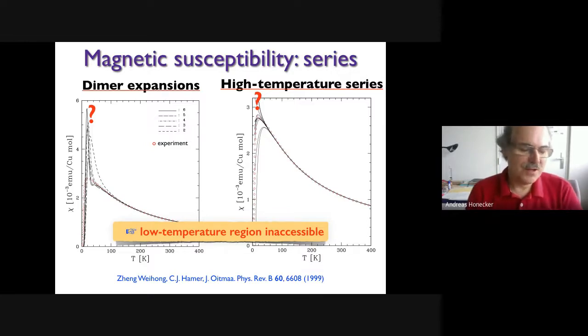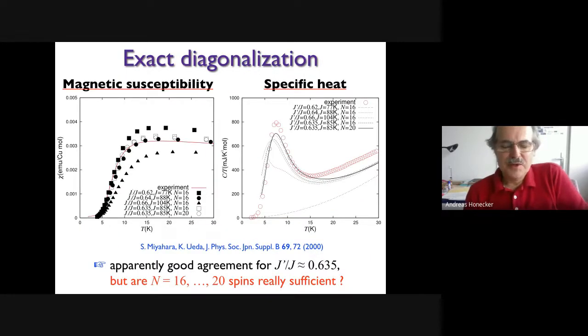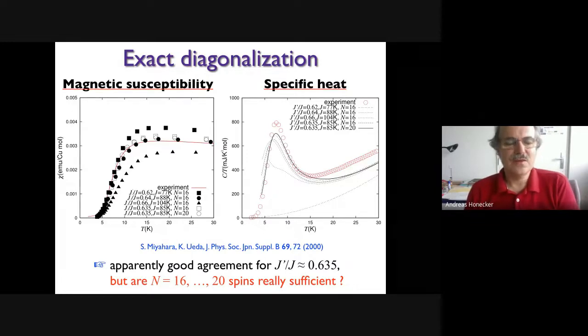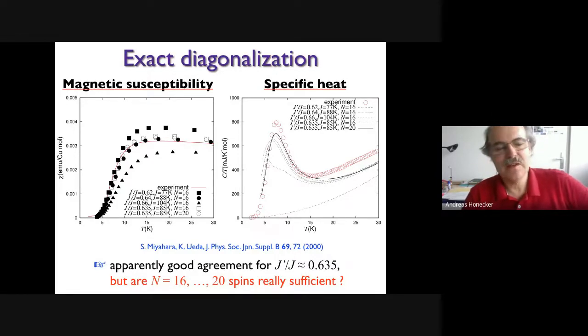So that was useful because, you know, I told you where strontium copper borate is located in the phase diagram. That location comes from such an analysis, but unfortunately you don't get to the low temperature regime by that method. So people tried something else. In the early days, they tried exact diagonalization. And here, again, red is experimental data and black is the theory from that time. Left is magnetic susceptibility, right is specific heat. They were claiming that the fit here for a coupling ratio of 0.635 should do the job.